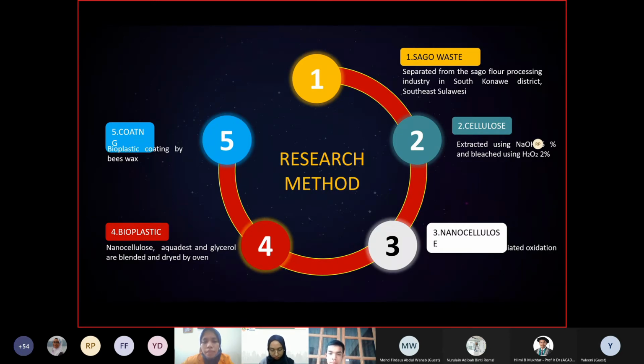And the fourth step is bioplastic production. Nanocellulose, glycerol, and aqueous were blended and dried in an oven. And then the bioplastic was coated with beeswax. The coating process was carried out by the immersion method. The resulting bioplastic has a water-repellent characteristic, and is more transparent and stronger.